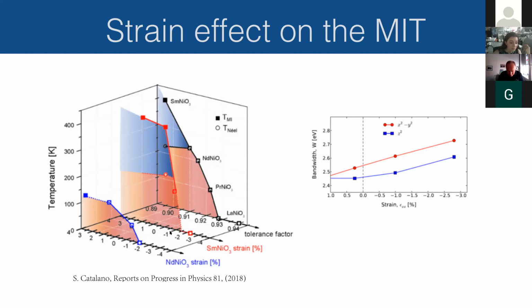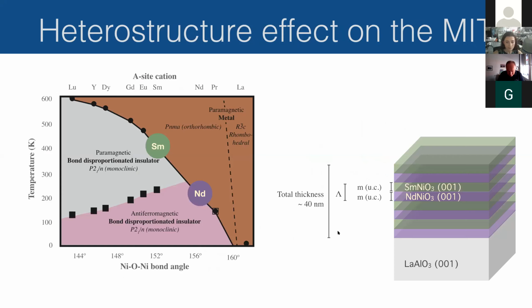And this makes sense because heterostructuring, as we know, does change the structure. It changes the bond angles and the bond lengths. So overall, the nickel-oxygen overlap will be different, the hybridization will be different, the bandwidth changes, and as a result, you have a strain effect on the electronic properties. So it's not really surprising that the metal insulator transition temperature and here the Néel transition temperature are affected by this. But what I wanted to talk about in a bit more detail is something that is perhaps more surprising.